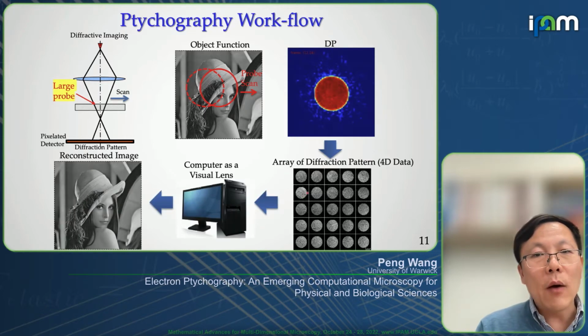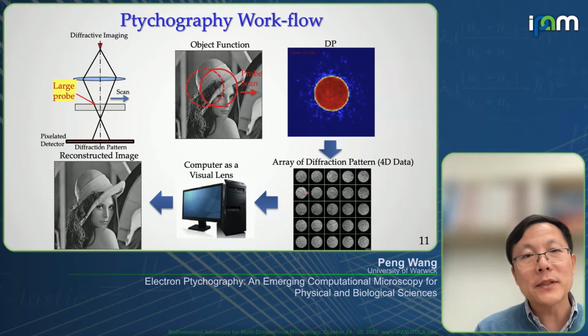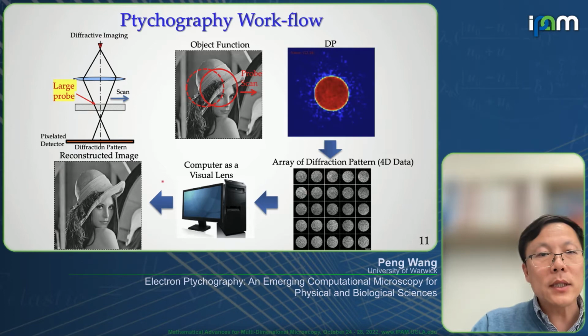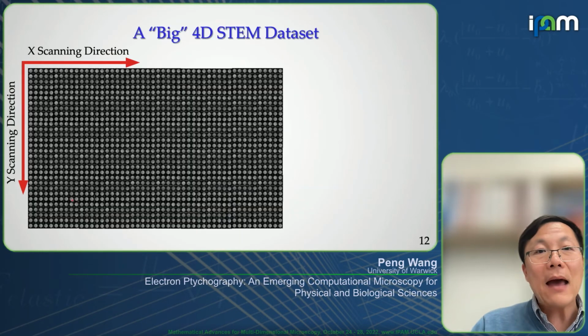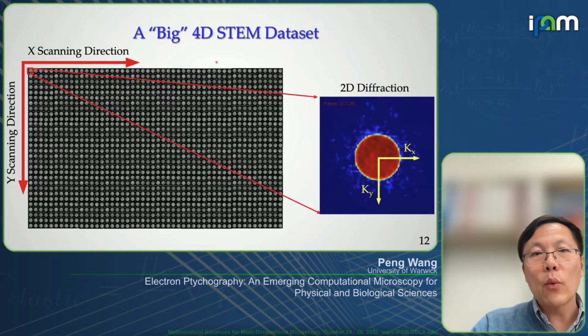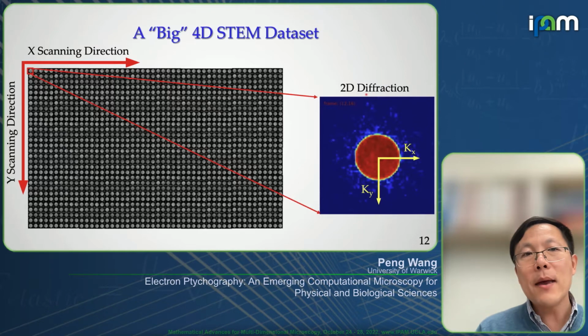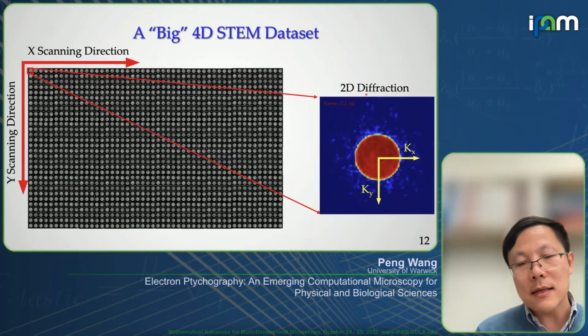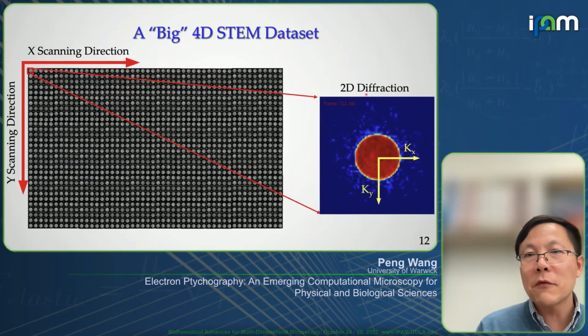And we get a so-called four-dimensional data set. Using this data set, we use a computing algorithm to reconstruct the object function. This is actually a big data set. As you can see, we scan in two dimensions, and at each position, we have a two-dimensional diffraction pattern. So this is a big 4D data set. And there are many people using different algorithms to extract information.